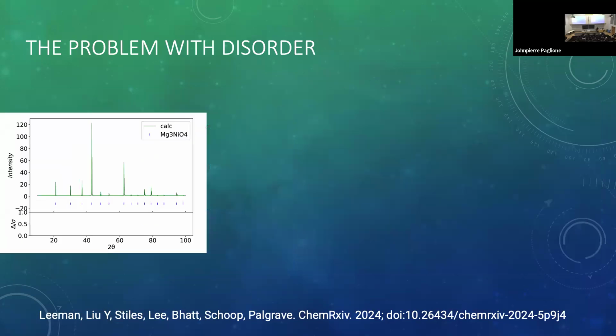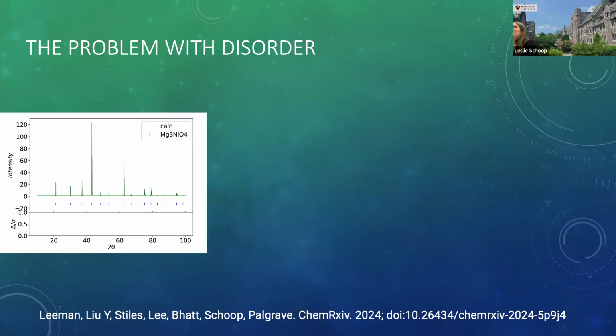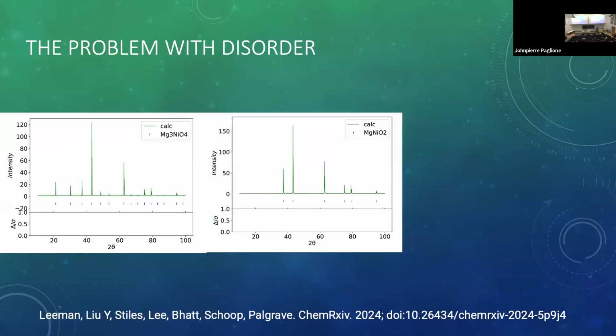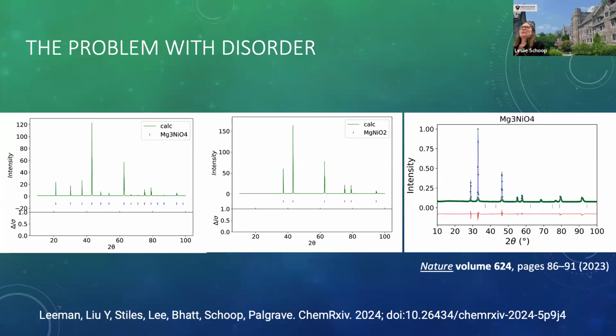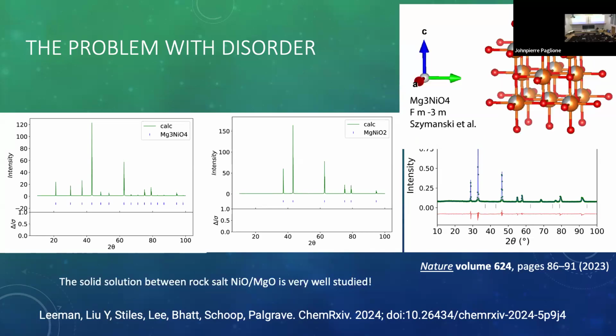So now if I simulate powder X-ray diffraction of those, this is my simulated powder X-ray diffraction of the primitive structure. This is of the face-centered structure, and you see they're very different. And now I compare it to the material that was made in this paper, and you can tell me which one they made. It's very obvious, right? So that's definitely not the primitive cubic structure, that's the face-centered cubic structure. So they made a material, if I assume that their stoichiometry is correct, although they didn't do chemical analysis, they probably made a version of magnesium 3 nickel O4, but in this face-centered structure. And so would that be a new material? Because on the ICSD I found only the 50-50 version.